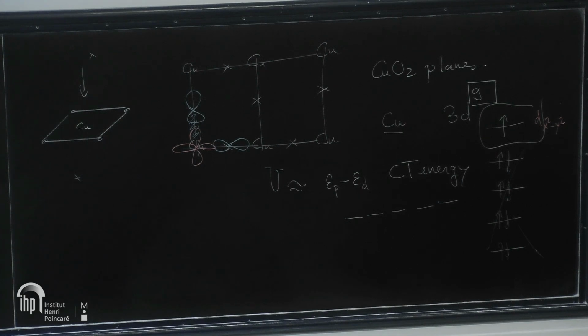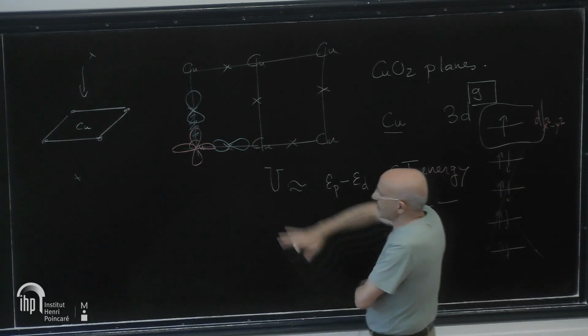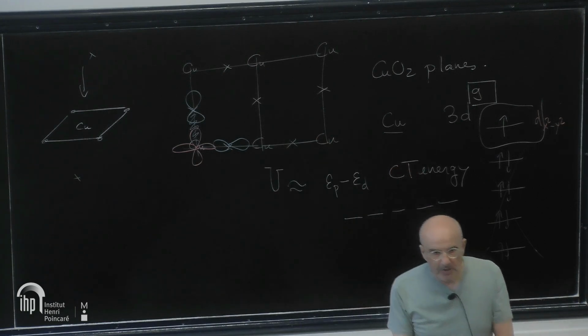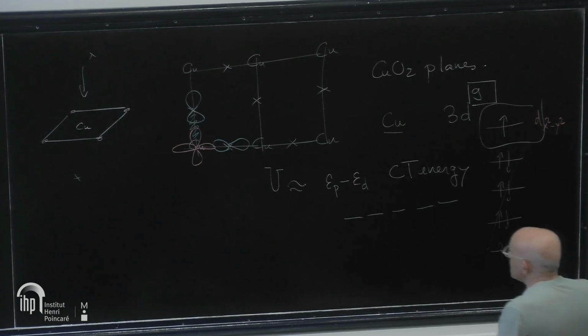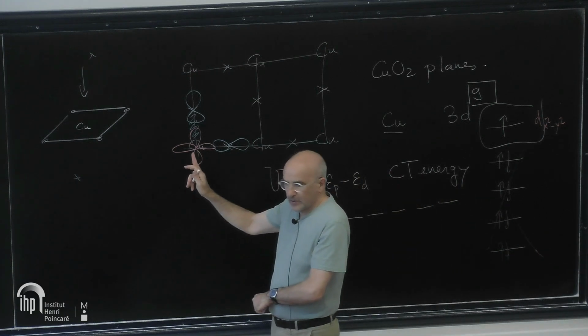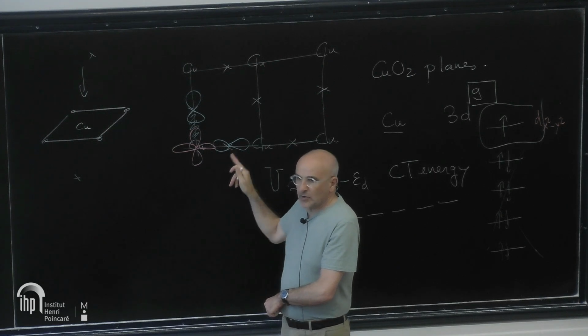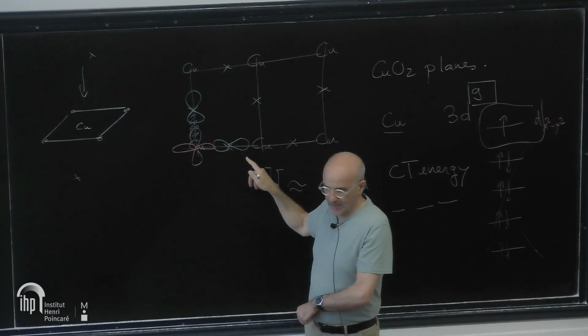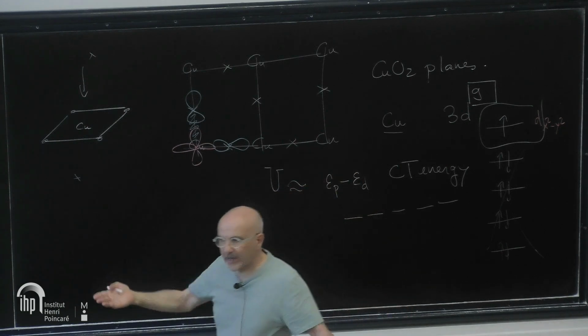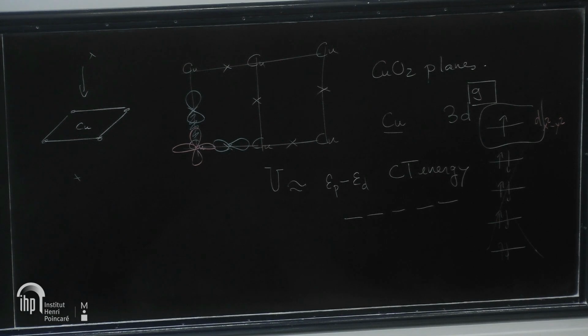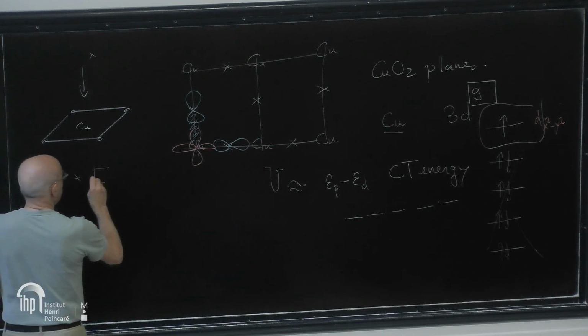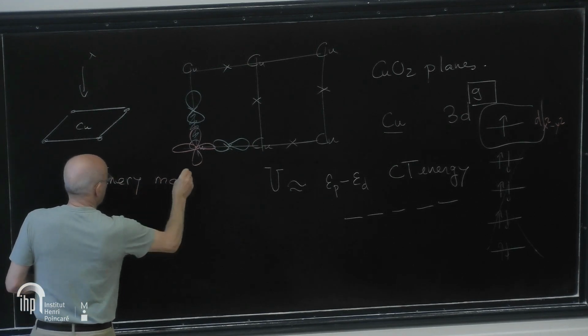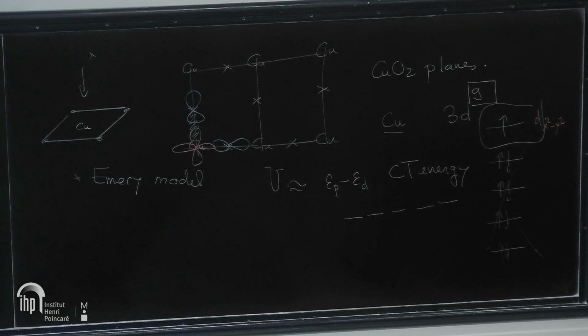So it is a long-standing debate in the field whether it is legitimate to reduce this problem to a single-band Hubbard model. Obviously, from the drawing on the board, it looks a little bit more reasonable to keep both copper and oxygen orbitals, which will then bring 1, 2, 3 bands in the problem, to write a generalized form of the Hubbard model that would contain a U on the copper, charge transfer energy, a hopping TPD between copper and oxygen. This is the so-called 3-band model, often called the Emery model. To start from this, study that model, and perhaps reduce it in some regimes to the single-band Hubbard model.